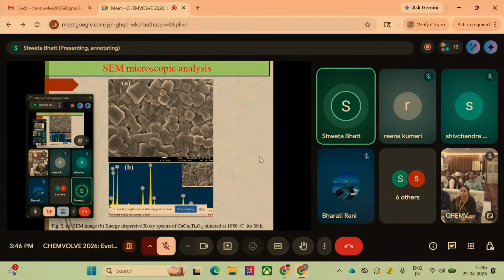As we have discussed already, the morphology of the CCTO is bimodal in nature. Bimodal means there are two types of grains, big grains and small grains, and there is a grain boundary here. So in the case of grains and grain boundary, we have discussed the IBLC. IBLC means the internal barrier layer capacitor. In the internal barrier layer capacitor, the material shows a high dielectric constant, and the grain boundary is insulating in nature.